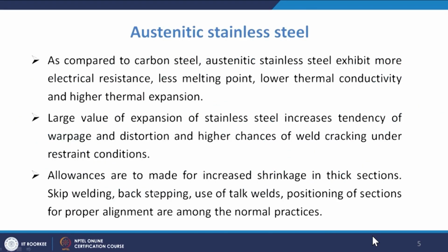Okay. Compared to carbon steel, austenitic stainless steel exhibits more electrical resistance, a lower melting point, lower thermal conductivity, and higher thermal expansion. The larger expansion of stainless steel increases the tendency of warping and distortion and the chance of weld cracking under restraint conditions.